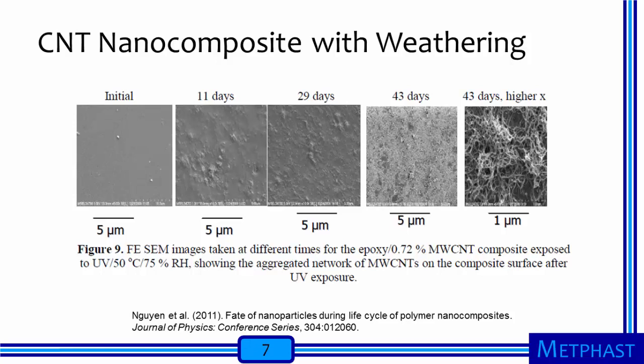What does it look like when a carbon nanotube nanocomposite breaks down by weathering? Nguyen and co-authors created a nanocomposite from an epoxy resin containing embedded multi-walled carbon nanotubes. They then exposed their test material to high-energy ultraviolet radiation, 480 watts per square meter, at 50 degrees Celsius and 75% relative humidity for 43 days in an accelerated aging test.